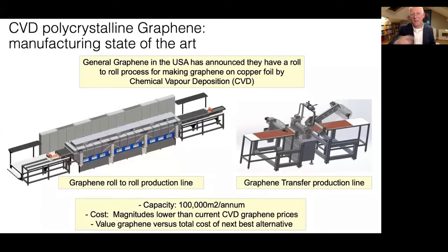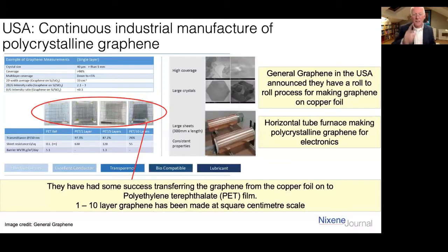This production line is another roll-to-roll production line in the USA, General Graphene. They've created graphene on copper foil in a horizontal furnace, and then they've solved the problem of getting the material off the copper onto a transfer sheet, and then they can transfer that to other machines. They've got a capacity now; in the first quarter of next year, they'll be making 100,000 square meters of graphene. Remember, 16 years ago, this was impossible. And this is what it looks like. Inside the red circle, on the left-hand side, we've got polyethylene terephthalate film, which is plastic bottle stuff, that clear plastic. We've then got one layer of graphene grown on it and transferred onto it, 5 layers, 10 layers. So these guys are not only growing the graphene at scale, they're doing the transfer at scale too.